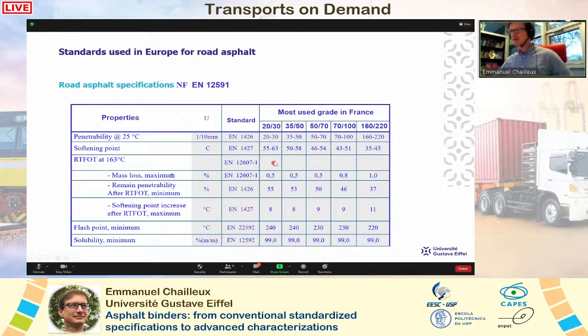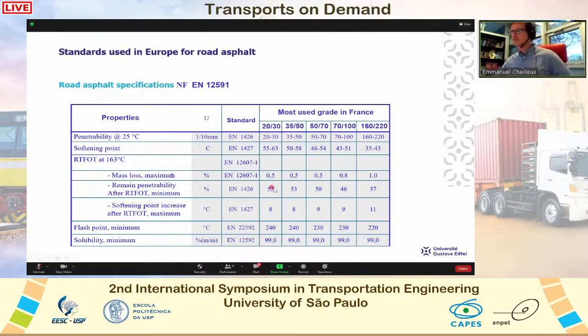And what is very important is what happens after aging by RTFOT. The mass loss during this aging process has to be below 0.5%. The remaining penetrability in percent has to be above 55%. The penetration and the softening point must not evolve too much. The softening point increase has to remain below 8 degrees for this one, 9 for this one, and 11 for this one. So you see that the specification for road asphalt is very simple in France and is measured using empirical tests like penetrability and softening point.